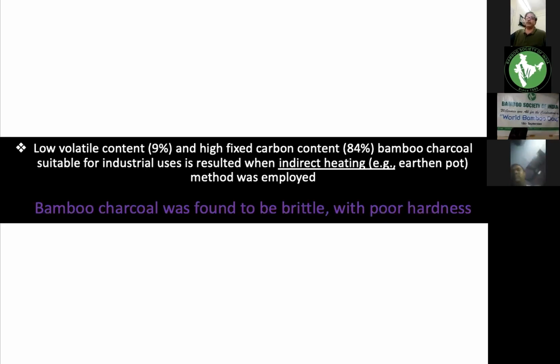So the inference is that when we use the country methods, we get products with a little bit higher volatile content, which is required for fuel purposes. We require it to be burnable. So a little bit higher volatile content is necessary for domestic use, whereas for industrial purposes there is more fixed carbon and fewer volatiles. So theoretically it shows that self-firing methods are suitable for producing charcoal for domestic purposes with a little higher volatile content, and the indirect heating method produces charcoal of slightly higher properties suitable for industrial applications.